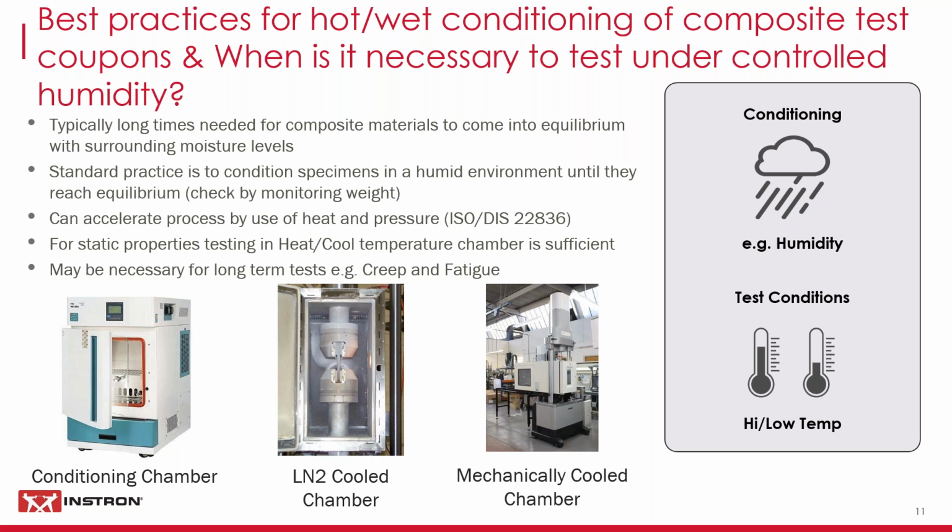Not something that Instron supplies, the conditioning chambers. We supply chambers for the testing machines. So it is possible to accelerate that process by using basically an autoclave, using heat and pressure. And there's a new ISO standard which is currently being discussed in committee that is going to standardize those techniques of accelerated conditioning.